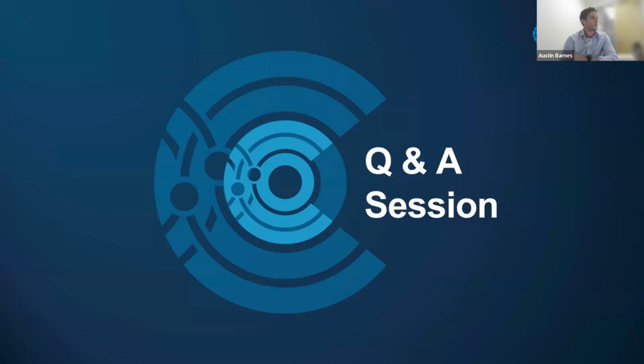Mm-hmm. One question, I am fascinated. It's crazy how you can get lateral resolution that's less than 5 nanometers, especially with some of these tips, right? These are platinum coated tips usually. Sure. So the radius of curvature is around 20 nanometers. So how can that be, where the lateral resolution is actually better than the topography itself?